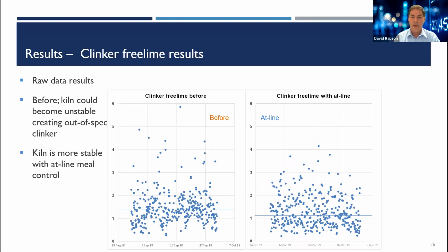So here's the raw freelime data from the kiln. There's a broad spread in the data and it shows some very high freelimes indicating still kiln instability. Once the at-line system was in control, it's obvious that the kiln is more stable and there are fewer high freelime values.